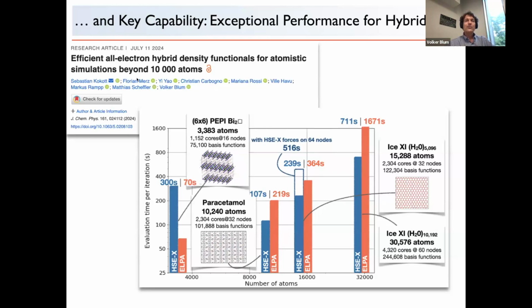Eventually, through numerous optimization steps, this allows us to do something like a 3,000 atom hybrid perovskite calculation with spin-orbit coupling, with band structures on a real existing machine. This is about 1,000 CPU cores on an Intel architecture, but this is a fairly standard setup that you can still get. This seems large, but you can see that the hybrid density functional here, which is in this case the HSE functional, takes about 300 seconds per iteration still. The eigenvalue solver also comes in with about 70 seconds.